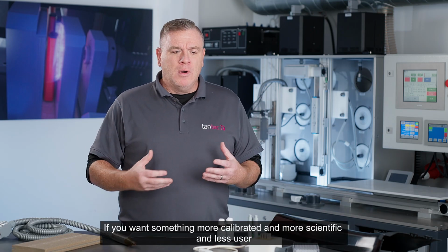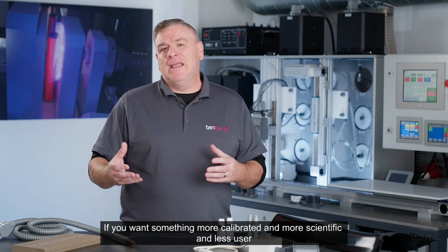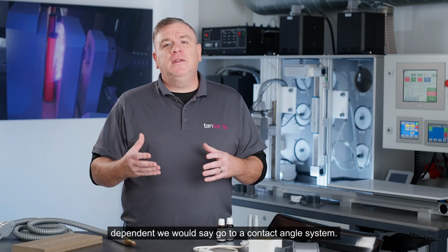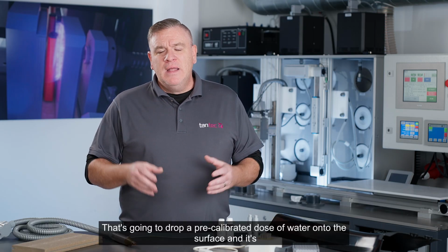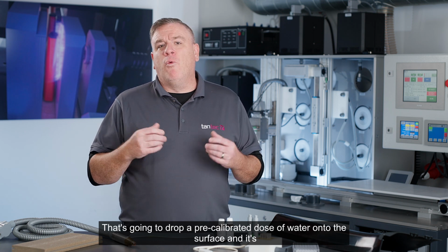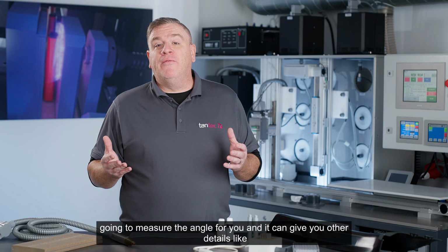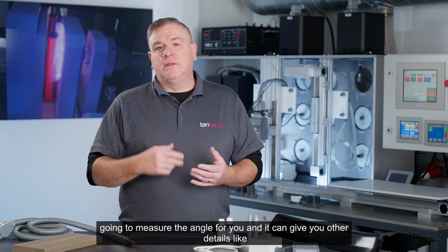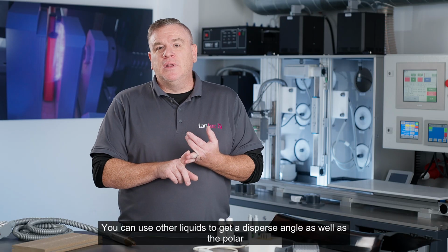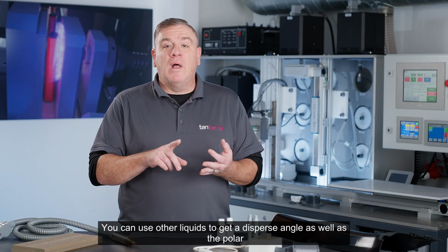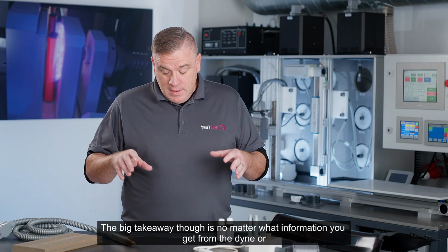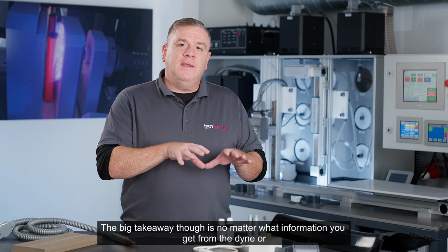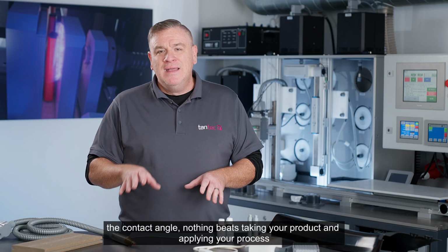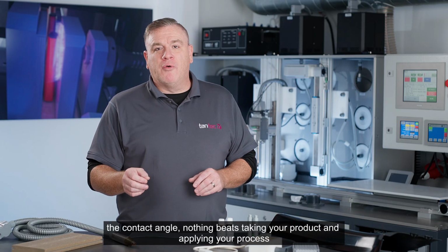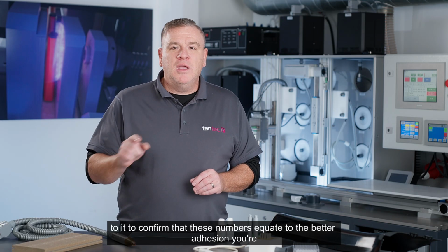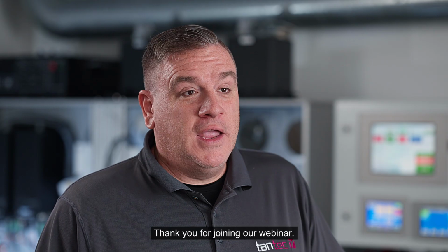If you want something more calibrated and more scientific and less user dependent, we would say go to a contact angle system. That's going to drop a pre-calibrated dose of water onto the surface, and it's going to measure the angle for you, and it can give you other details. You can use other liquids to get a disperse angle, as well as the polar properties of the part itself. The big takeaway, though, is no matter what information you get from the dyne or the contact angle, nothing beats taking your product and applying your process to it to confirm that these numbers equate to the better adhesion you're looking for.